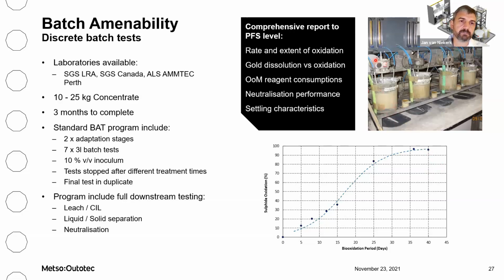The batch amenability test program will typically give you sufficient information for the pre-feasibility level study, including the rate and extent of oxidation, the gold dissolution as a function of oxidation, your order of magnitude reagent consumptions, and the neutralization performance, confirming that they'll produce stable arsenic precipitates, as well as settling characteristics for thickener design.